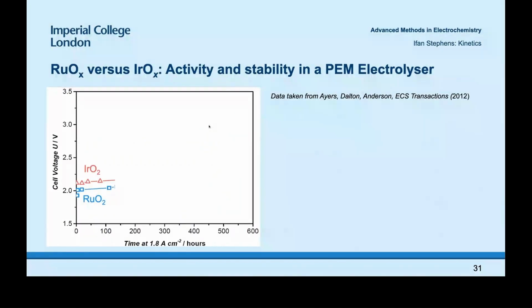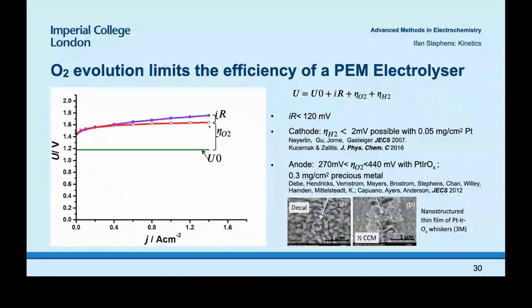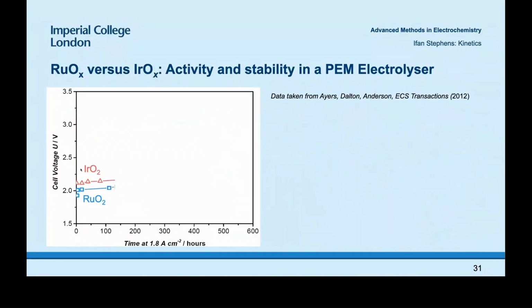And usually you'll use iridium-based catalysts for oxygen evolution. You can also use ruthenium. And here's showing how cell potential changes with time for ruthenium and iridium. You can see ruthenium works better at short times. This is at constant current. And then what tends to happen is over longer times, you start to see degradation in the performance.